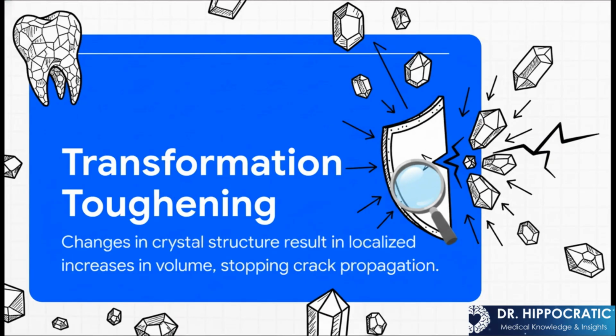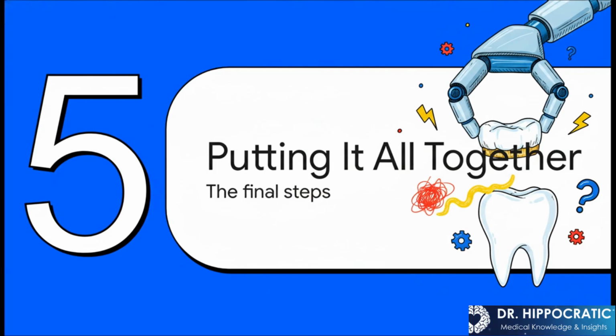But here's the absolute coolest part. YTZP has a superpower called transformation toughening. If a tiny little crack starts to form, the ceramic crystals right at the very tip of that crack instantly change their shape. They expand, creating this compression zone that literally squeezes the crack shut and stops it from spreading any further. It's like the material is actively fighting back to heal itself. How cool is that?